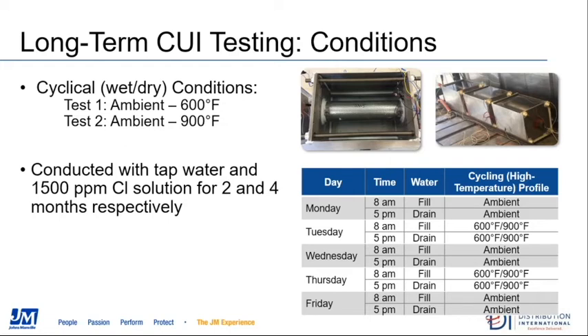So this test is meant to try to sum up 15 to 20 years of what pipes would see in an environment close to a body of salt water. And we're trying to boil that down to about 6 months. And really, in essence, we're trying to take the pipe specimens to failure and then analyze what happened. You can see that this is a cyclical test. So we ran test 1 from ambient to 600 degrees. Test 2 was run from ambient to 900 degrees.